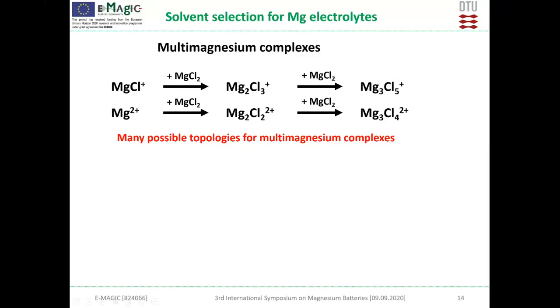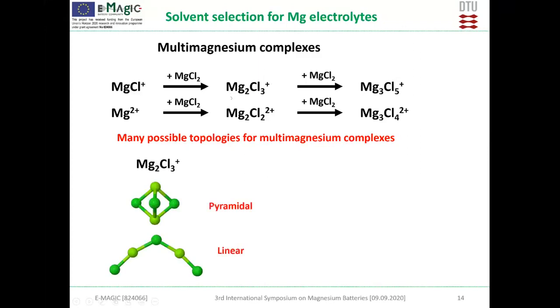So for example, if we look at this Mg2Cl3, we have 2 possibilities. One is the pyramidal, when you have 2 magnesium here and here, and 3 chlorines that are shared between these magnesium. And also it can be a linear one, with 1 chlorine that is shared between 2 magnesium and 2 chlorines that are just separated onto 1 magnesium each. And if we do the calculation, putting also solvent there, solvating the magnesium, we can see that we get the lowest energy structure for THF only if we consider these pyramidal structures, because THF has a more bulky structure, so it prefers that magnesium will be coordinated also by a lot of chlorines.